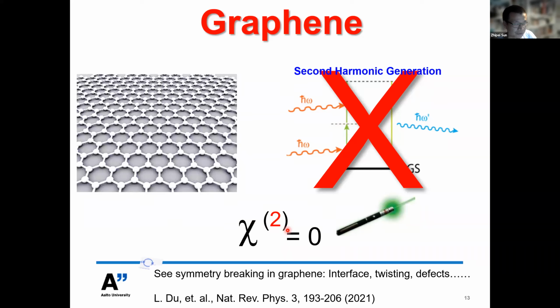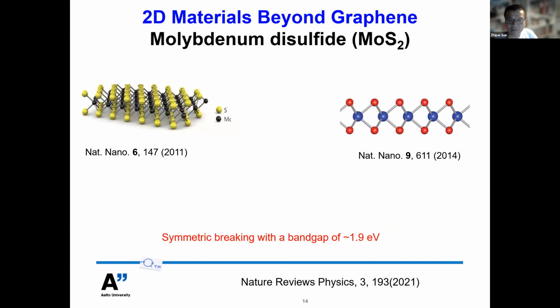However, people have tried different symmetry breaking methods, for example, using an interface, twisting, or using defects. You are able to introduce a second order nonlinear response. If you are interested, you can go to our recent paper. Anyway, if we look at other 2D materials beyond graphene, for example MoS2 here, this shows the atomic structure of monolayer MoS2. As we know, the two-H phase of MoS2 has a broken central symmetry. You can see from here.